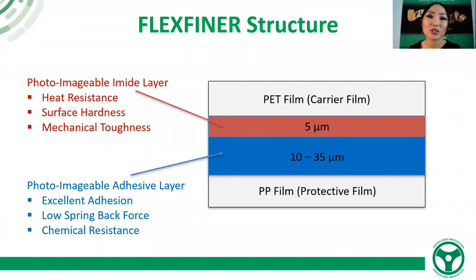Here we want to show you the structure of a FLEXFINER. You will have a standard 5 micron photoimageable imide layer on top that provide heat resistance, surface hardness, and mechanical toughness. Below is a 10 to 35 micron layer of a photoimageable adhesive. This layer provides excellent adhesion, low spring back force, and chemical resistance.